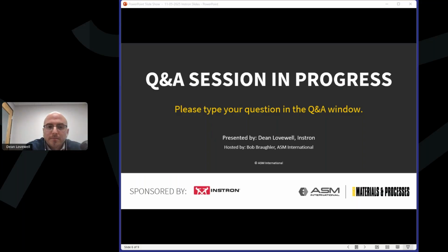Okay, thank you, Dean. We're speaking with Dean Lovewell of Instron. Does the same averaging principle apply to advanced high-strength steels where strain localization is thermally driven rather than solute diffusion driven? Yeah, that's a good question, because the averaging applies in the context that we're obtaining a more repeatable and representative R value, but the variability that we're removing is somewhat different. So with a PLC affected alloy, we're seeing width strain move along the gauge length of the specimen in these Luder's bands that you see on the specimen itself.